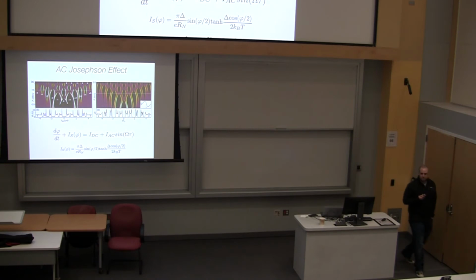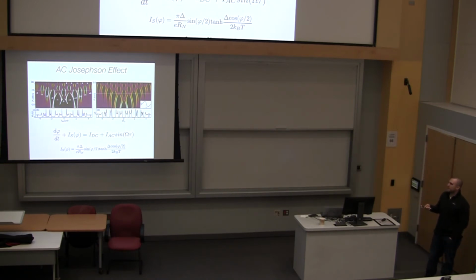So this is what I call the Shapiro step diagram. This is the bias current you put on. This is the power of the microwave frequencies you apply. And out of the board is dV/dI. Black is 0 dV/dI, so the superconducting regions. Now, if I apply a sinusoidally varying voltage to the Josephson junction, remember dφ/dt is equal to V with some constant. So if that V is sinusoidally varying, φ of t will also be sinusoidally varying. So if I put in sine of a sine, what you end up getting out is Bessel functions. So the power dependence of each one of these plateaus should be Bessel function-like, and that's exactly what you see.